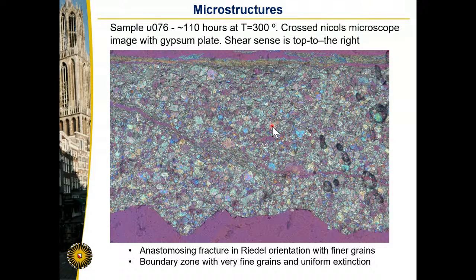So the bulk of the sample has these quite large dolomite grains. I see that there's no scale bar, that's really terrible. But the entire thickness here is about 800 micron. So we have this very narrow zone where the grains cannot be recognized anymore, suggesting that they are very fine-grained, indeed below the wavelength of light.